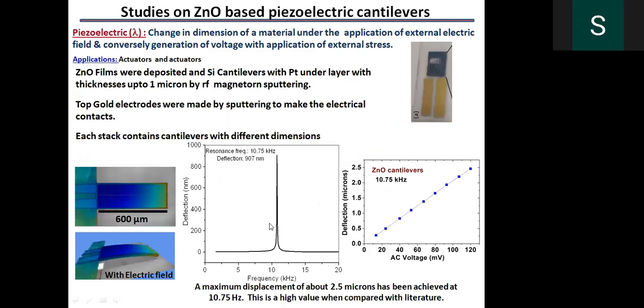We also deposited the piezoelectric material, namely zinc oxide, and we also saw a similar deflection with application of an electric field, and we have a huge deflection of around 907 nanometers at 10 kilohertz reference frequency.